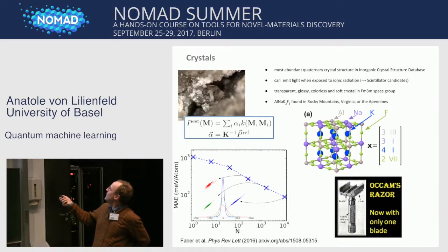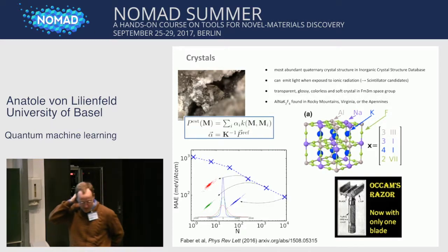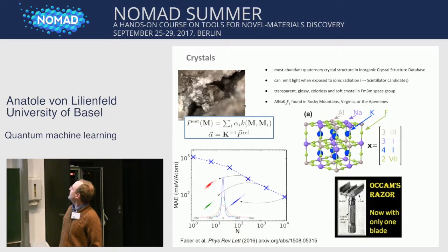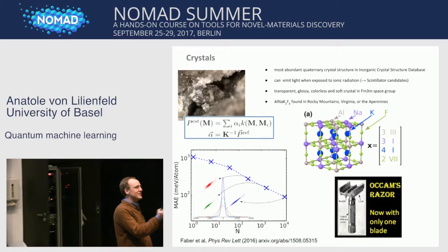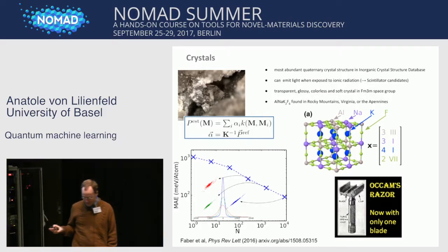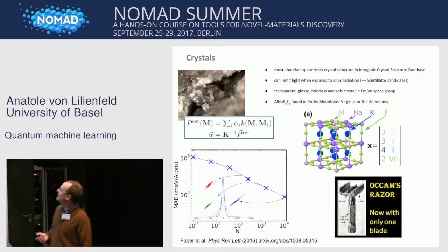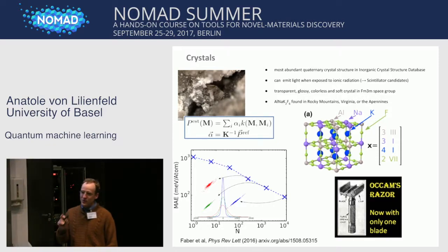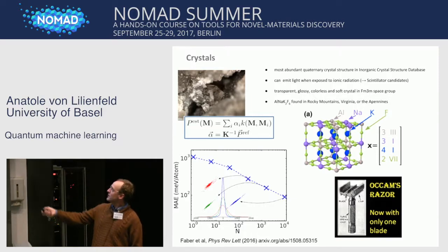You can think of them as a vector which contains, for each elemental type, the coordinates in the periodic table, so the group and the period. And since you are looking only at the elpasolites for this one crystal structure, you don't need to specify coordinates. It's implicitly in that information. And so if you train the machine just on elpasolites, it's perfectly fine. It's within that domain that the machine will work. And this is something we could show.